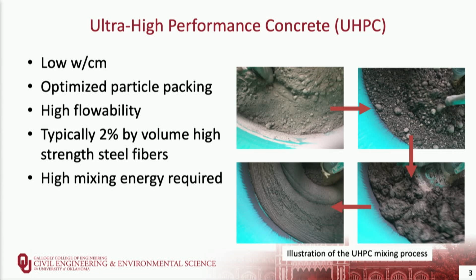To get ultra-high performance concrete, we have a low water cementitious materials ratio. We optimize the particles within the mix. We don't include coarse aggregate to create a more homogeneous material. And then we typically include 2% by volume of steel fibers, but sometimes it can be more than that or less. Because we don't have that coarse aggregate, it does take more mixing energy. And so this is an illustration of mixing ultra-high performance concrete where you start with a very dry powder material. You add the water, and it still looks relatively dry. You start to get cement balls forming, and by the end of it, you get what I refer to more like pancake batter, Walt referred to as molasses, but it's a very flowable material.